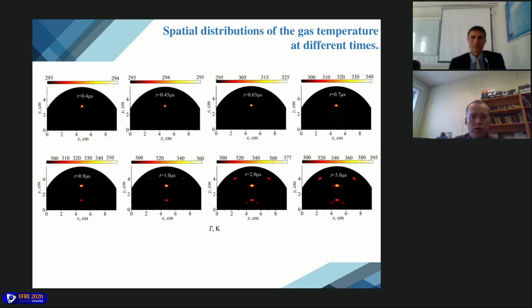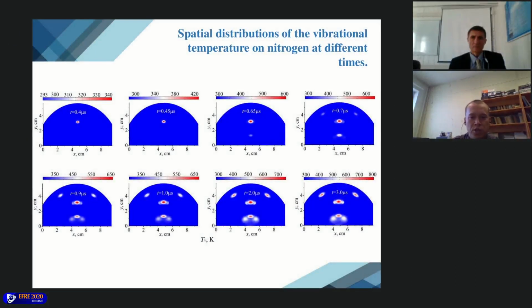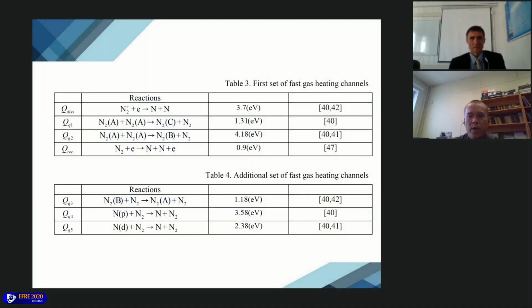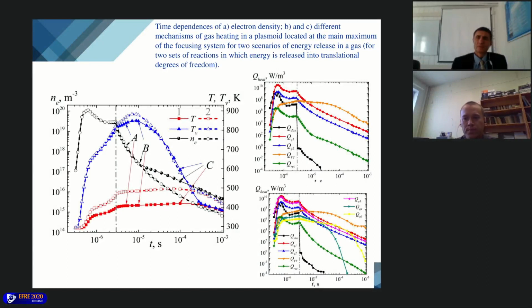The next slide shows the spatial distribution of the vibrational temperature of nitrogen at different times. As we see, at the time of 3 microseconds, the vibrational temperature reaches 500 kelvins. In the case of using the second set of gas heating mechanisms, including the processes presented in these two tables, the picture remains qualitatively the same. 4 plasmoids are formed. However, the quantitative characteristics, in particular the vibrational temperature and gas temperature, became higher.